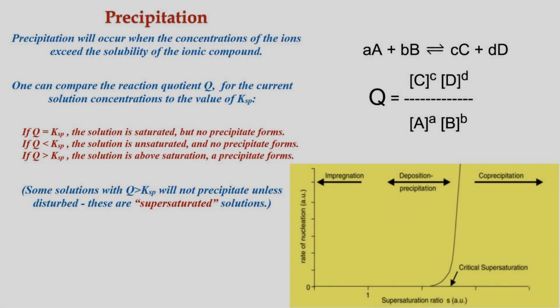Thus, there is an essential critical supersaturation concentration below which nucleation is very slow and above which nucleation is very fast. The range between this critical supersaturation concentration and the solubility concentration is the domain of deposition precipitation, while impregnation is performed in the concentration range below the solubility limit. Especially for a multi-component system, it is important to operate at a high supersaturation level so that the solubility product of all products is simultaneously exceeded.